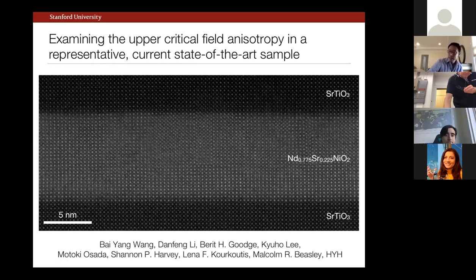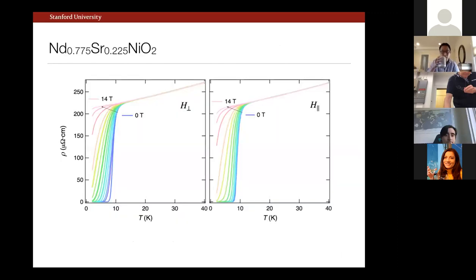But since this is kind of the cleanest thing that we can reproducibly synthesize, let's use this as a focus of studying the upper critical field. So the experiments are simple. We're just looking at the resistive transition in the magnetic field. I can go into more details if you like later in the discussion, but for what I'll show you, we'll just use 50% of the normal state as a criterion or proxy for the upper critical field in the system, both in the perpendicular and parallel direction.